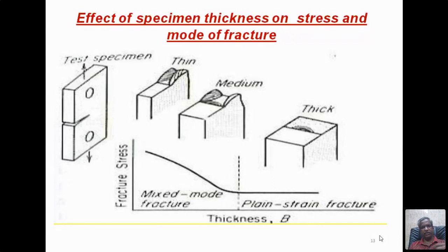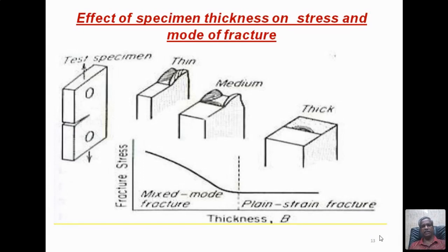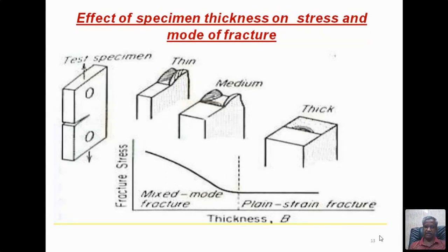After a critical thickness, plane strain fracture occurs and the fracture stress remains constant. Below that critical thickness, you get mixed-mode or ductile fracture. For fracture toughness testing, you need the specimen to be in the plane strain fracture condition — not plane stress or mixed-mode. If fracture stress varies with thickness (e.g., 500 MPa at 10 mm, 400 MPa at 15 mm, 300 MPa at 20 mm), it is not a material property. A true material property must be independent of specimen thickness.